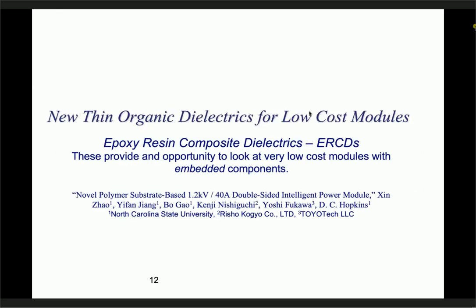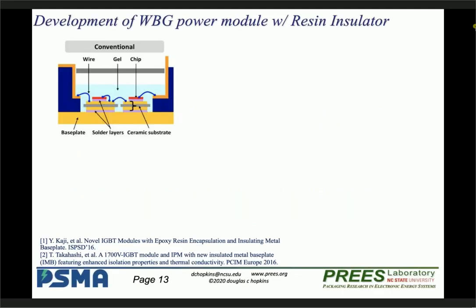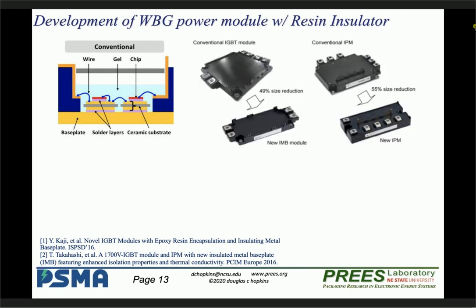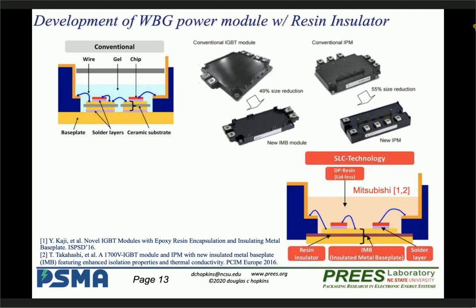Now, I know I'm kind of rushing quickly because I want to get to Shixuan. He's the star for this show. But I want to give a little background on these epoxy resins that we've been looking at. Traditionally with the DBCs, you have a heavy base plate, you solder down your DBCs, which have your die on top. But instead, what Mitsubishi did 2 years back in 2016, here's the references, they decided to go with what we're doing, the epoxy resin. They say a resin, but it's an epoxy resin.